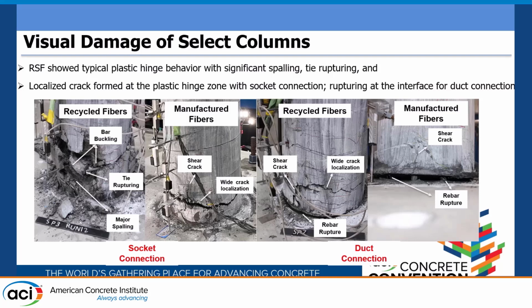It's pretty much different from the manufactured fiber. You see a wide crack localization in the plastic hinge. We kind of expected that, because a lot of the trend now is that crack localization happens in failure of UHPC. This is for the socket connection, by the way. For the duct connection, because the column was so stiff, my argument is that the failure happened at the interface, where the reinforcement ruptured at that point.